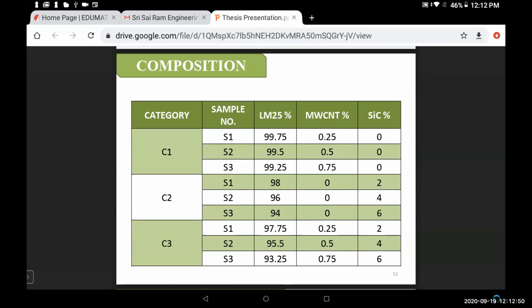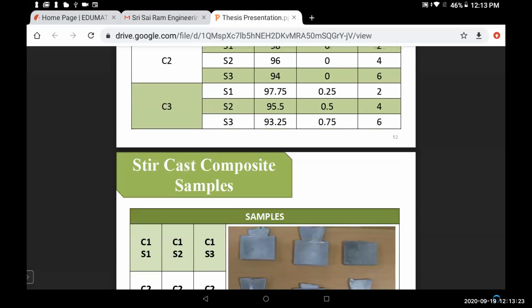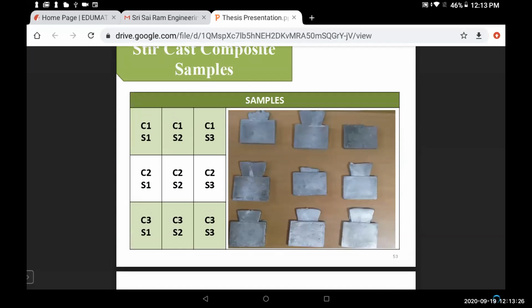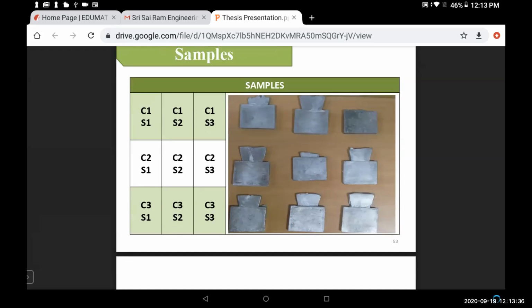And these are the various percentages of multi-wall carbon nanotubes and silicon carbide reinforcement. In C1 we used only CNT with 0% silicon carbide. In C2 we used 0% CNT and 2, 4, 6% silicon carbide. In C3 we used both 0.25, 0.5, 0.75% multi-wall CNT and 2, 4, 6% silicon carbide. So you can do a lot of combinations, depending on the cost involved as well as the time of fabrication. These are the various samples manufactured: C1S1, C2S2, and C3S3 with pure CNT, pure silicon carbide, and the silicon carbide and CNT combination.